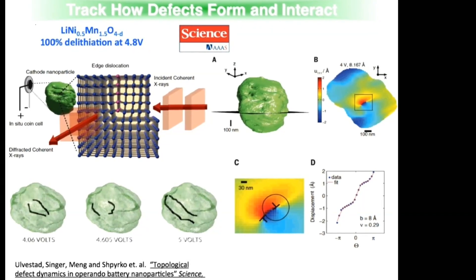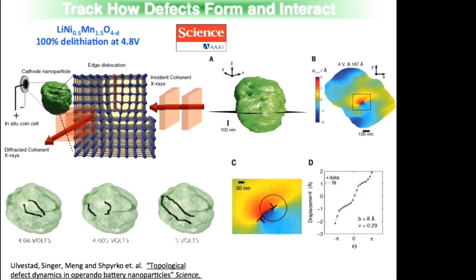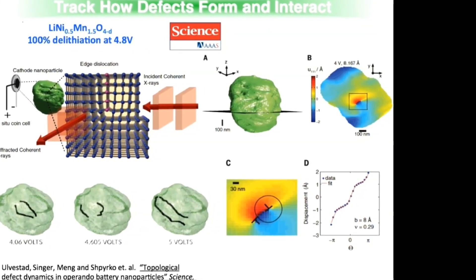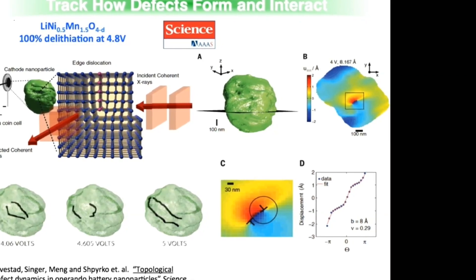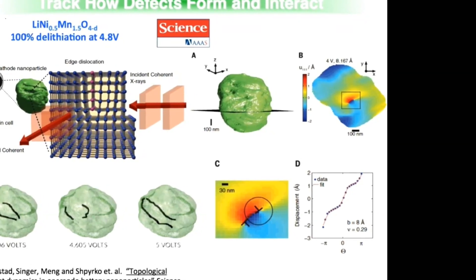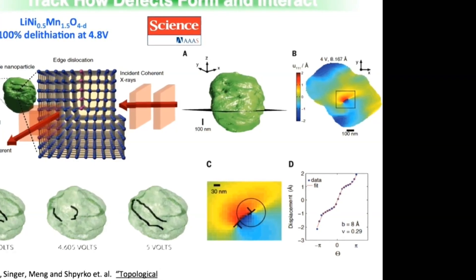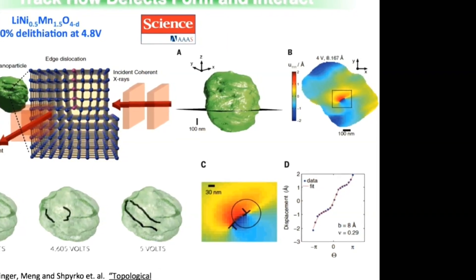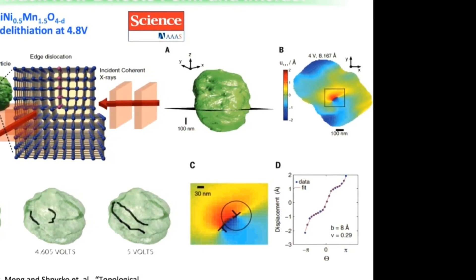What's actually happening is that the lithium ions exit and enter cathode nanoparticles, which is what causes them to expand, contract, and degrade. I was really excited to get this feedback because it means everything else in the video passed the scrutiny of one of the world's leading battery experts.